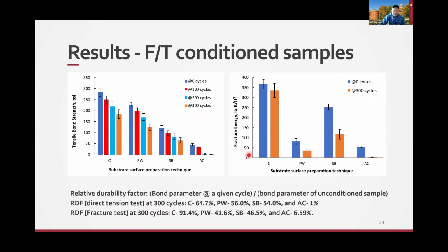The ASTM says after 300 cycles the dynamic modulus is supposed to be retained at 60% or higher, which we don't have. If we use the strength as an indicator and keep the 60%, only the chipped method can give you 60% or higher retention after 300 cycles of freeze-thaw.